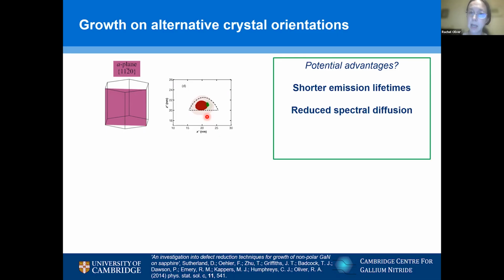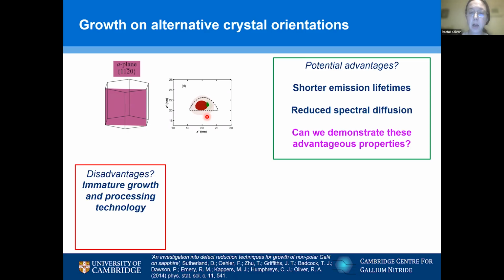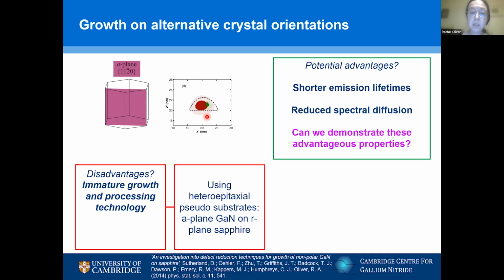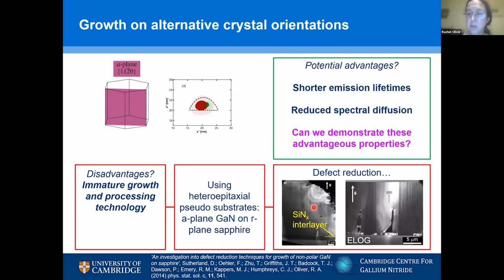So one of the first questions I'm going to ask in this talk about growing quantum dots on this non-polar crystal face is: is this true? Can we demonstrate these advantageous properties? I've got other questions to ask though, because we're really good in the nitride community at c-plane growth, but other crystal orientations like the a-plane that I'm showing here, we're a lot less good at that. So with this immature growth and processing technology, we've got to deal with the fact that we're doing heteroepitaxial growth in a new orientation, and we've got a load of defects, not just the dislocations I showed before, but also another family of defects, planar defects called stacking faults. So given that this is an immature growth technology, can we make any useful devices at all? And those are the two questions I'm going to answer in the rest of this talk.